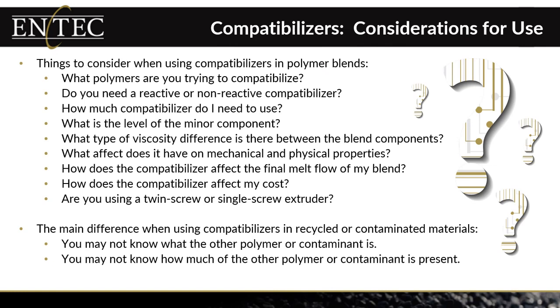Again, how much compatibilizer do you need? Once again, it depends on the percentage of the two polymers that you're blending and what those two polymers are. Because for some of them, some polymers are much easier to compatibilize, while other polymers might require higher loading levels to get good compatibilization. So that's something you need to consider. What is the level of the minor component? Well, obviously you know that, but that minor component might be 10% or it might be 50%. So obviously it's important to note there because the higher levels might require higher levels of that compatibilizer.